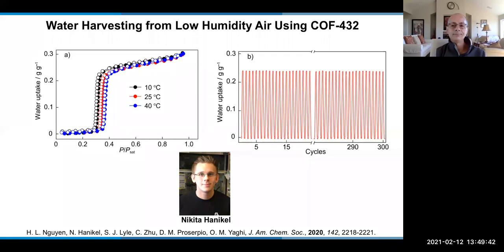The reason I'm showing this example is that the crystallinity of COFs is not just for characterizing the COF, but also sometimes it's extremely important for properties. If this COF is not crystalline, the water uptake behavior will not be a step behavior. We've studied this in MOFs, and we find that water molecules crystallize or form small crystalline seeds inside the MOF. And in this case, the same thing is probably happening, we're still studying it, in the COF. And if the COF is not crystalline, you're not going to form an ordered network of water seeds, and therefore you will not get this cooperative step behavior, which is what you would need to make a viable water harvesting material.